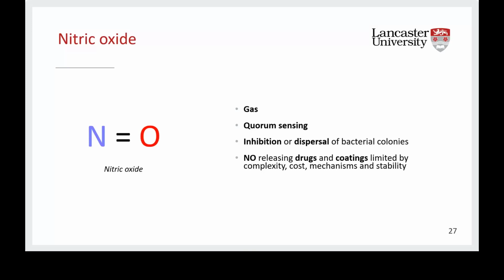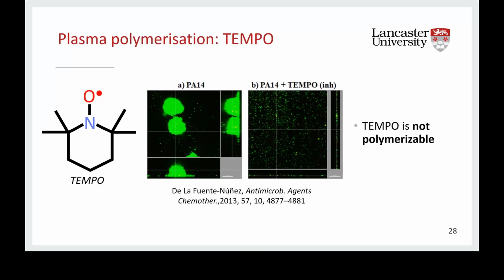There are several NO-releasing drugs and coatings. However, they're limited by complexity and cost. But the point is that nitric oxide is extremely reactive, so it is extremely short-lived. Scientists have discovered other molecules which have similar properties. One of them is TEMPO. TEMPO is a nitroxide radical, so it has an NO functional group like nitric oxide. But this time there are 4 methyl groups, 2 at the left and 2 at the side, that protect it and make it stable due to steric hindrance.